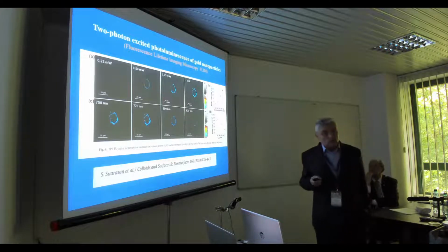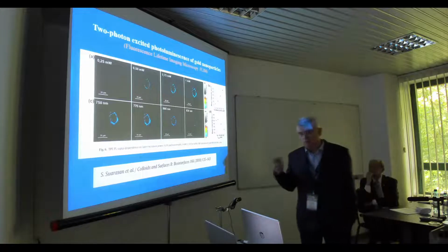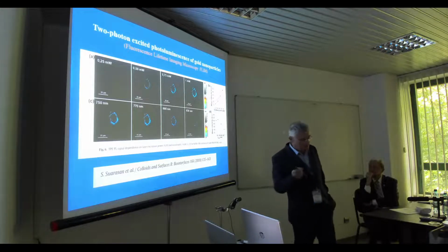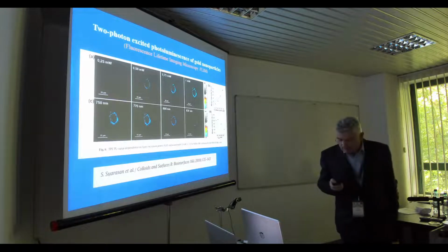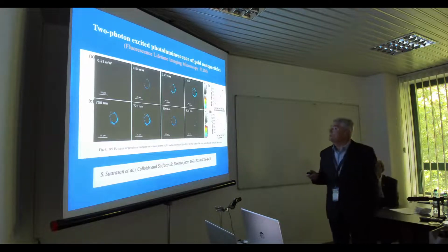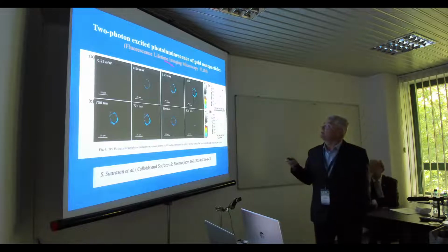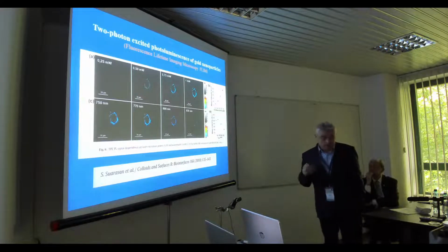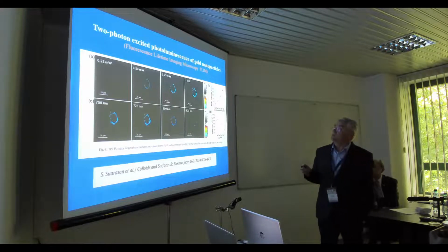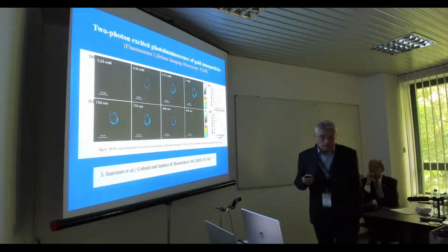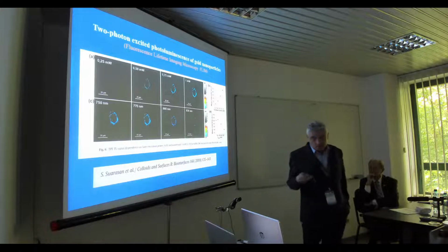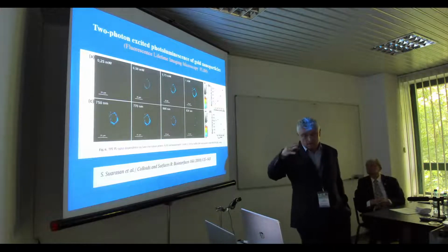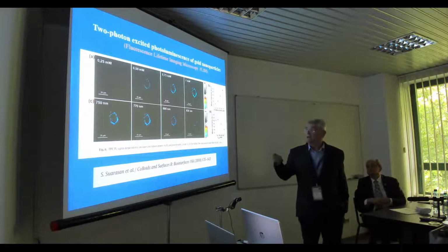Now, this is the intrinsic signal from the particle, but another interesting signal is luminescence. This was unknown for gold nanoparticles until about 10 years ago. They are also luminescent, though the term is luminescence, not fluorescence, when excited by two photons with a pulsed laser at 800 nanometers. By recombination and transfer between the sp band and the d band of the metal, they give light.